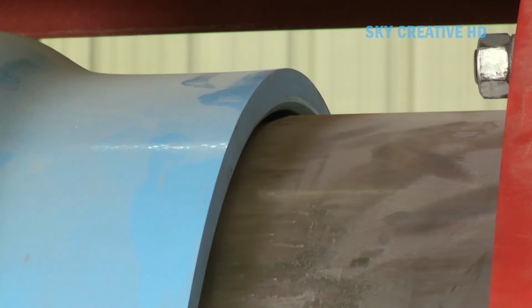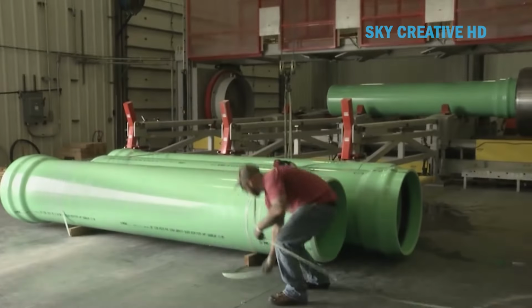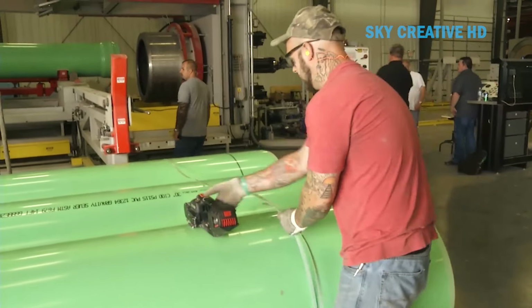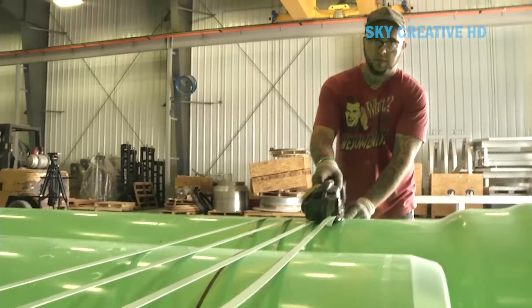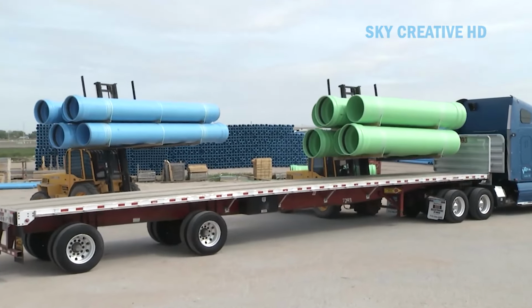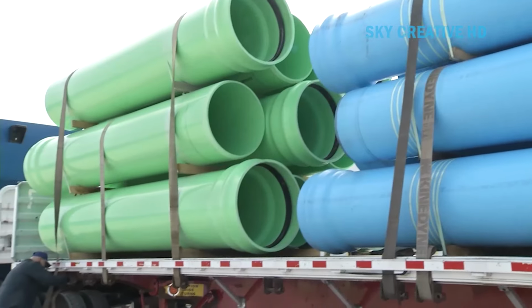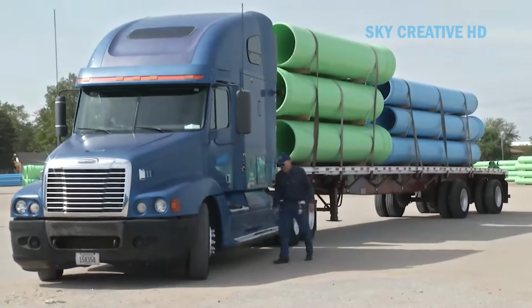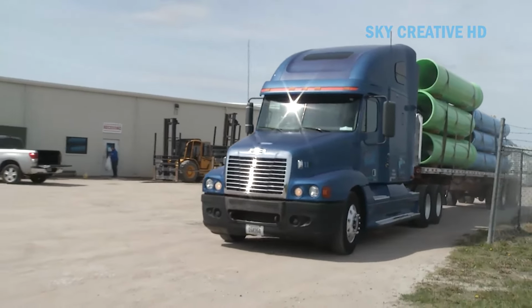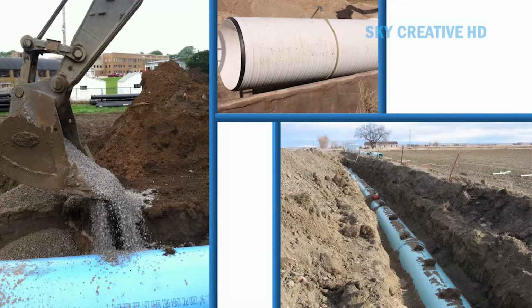Finally, it reaches the haul-off unit, a specialized caterpillar track system with rubber belts that gently grip the pipe, pulling it through the line at speeds around 3 feet per minute. The final station is the automated saw, which cuts pipes to standard 20-foot lengths. These cuts must be perfectly square, within 1 degree, to ensure proper bell and spigot joint assembly in the field. These pipes, meeting ASTM D3034 specifications, will serve communities for over 100 years. Now that's engineering for the ages.